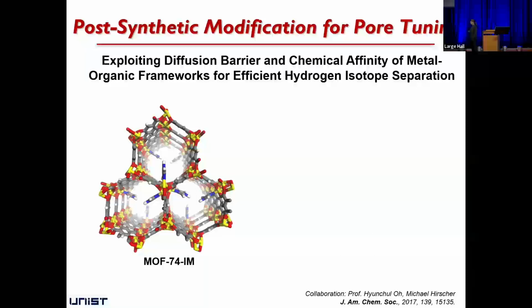But the problem is that the kinetic quantum sieving effect is based on quite weak physisorption. So only at low temperature can we operate this system. So to increase the operation temperature, we need to consider the chemical affinity quantum sieving effect as well. So we try to put the kinetic and chemical affinity quantum sieving effects in one system.